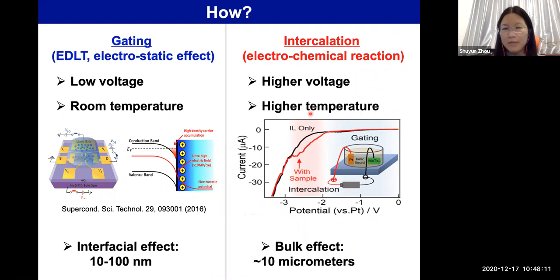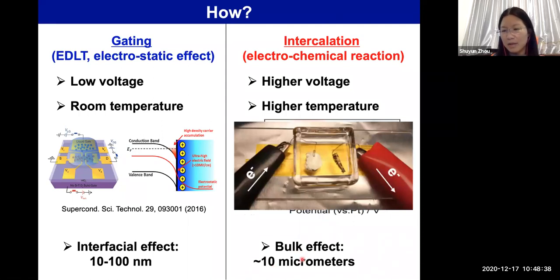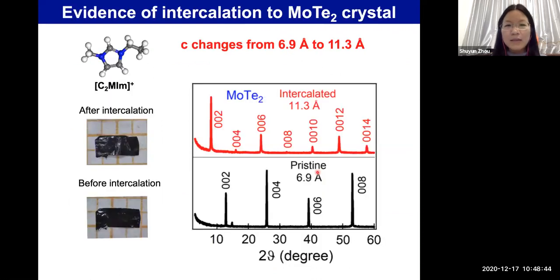And moreover, in addition to the difference in these experimental conditions, this intercalation method also has a major difference in that this effect is actually bulk sensitive. It applies to samples tens of micrometers thick. So it's actually a bulk effect. This is the device that we use for the intercalation. So let's see what is the effect of this intercalation on this molybdenum ditelluride.